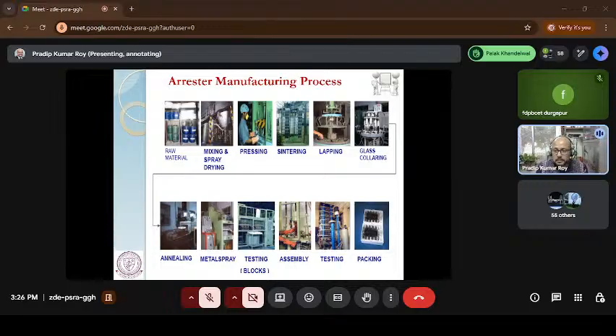What I said earlier is that the current ideally should pass through the block, not the side of the block, not the side of your porcelain part also. So it's mostly passing through that block. That's why we do some glass coating. Glass is the insulator here, an insulating coating around the block so that there should not be any kind of decay or maybe flashover from the side of the block.